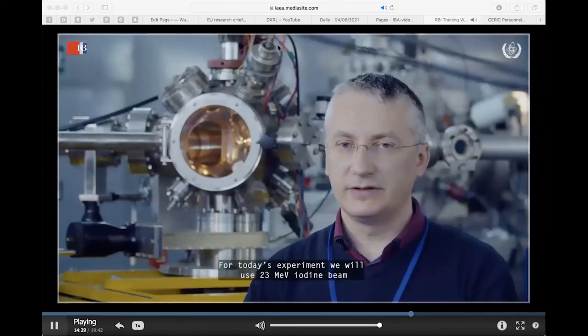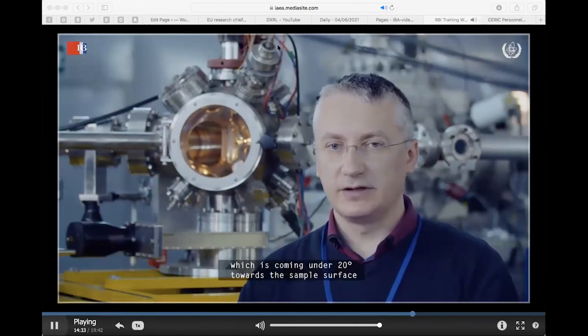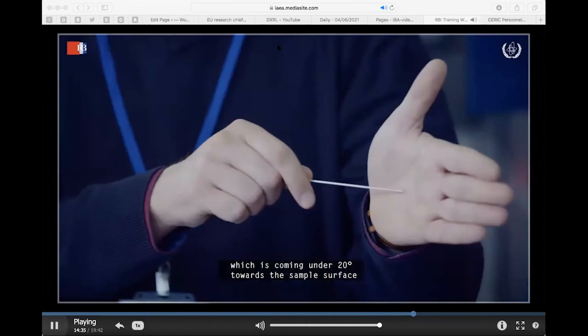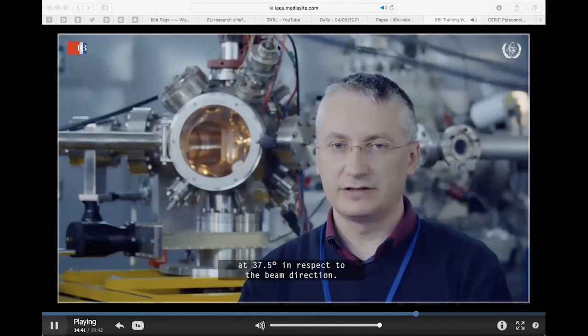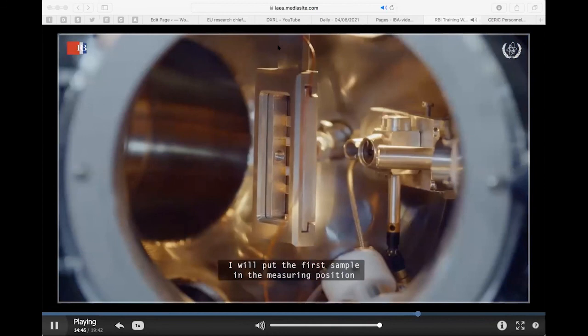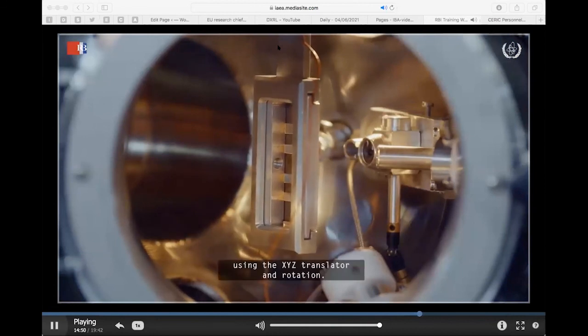For today's experiment, we will use a 23 MeV iodine beam, which is coming at 20 degrees towards the sample surface, and a time-of-flight ERD detector positioned at 37.5 degrees with respect to the beam direction. Now I will put the first sample in the measuring position using the XYZ translator and rotation.